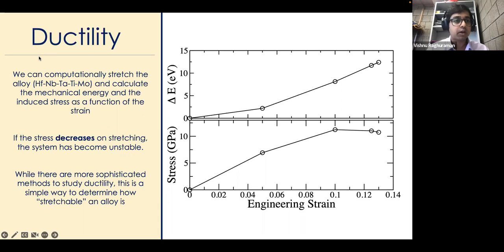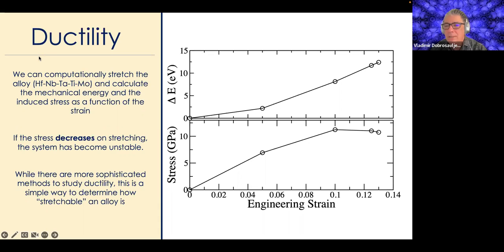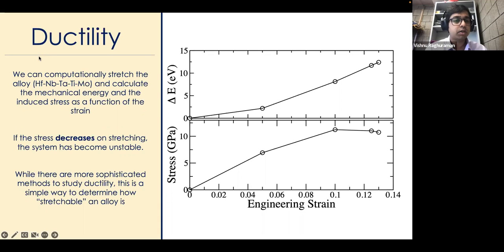For high entropy alloys, I've observed that. Is there a simple physical picture? Why is that? What exactly is the bottleneck? Because I think in simpler crystals there's not that much happening. But in high entropy alloys, I think there are dislocations and there are more defects when you relax at 15% strain, which is quite large.